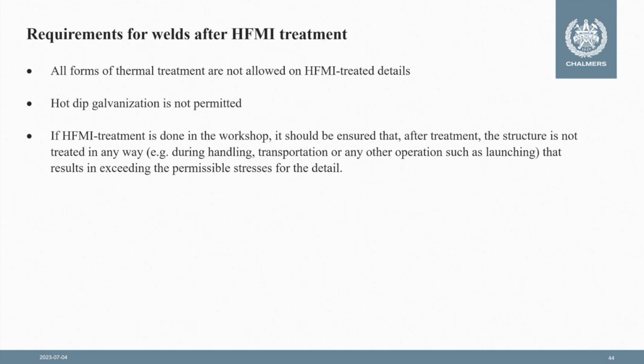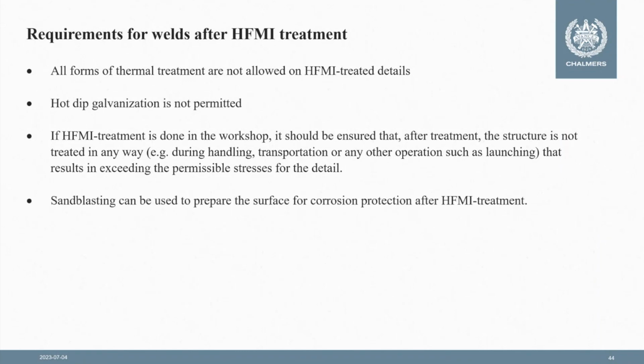If HFMI treatment is done in the workshop for new bridges, it should be ensured, of course, that no operation done results in a relaxation of residual stresses. For example, if the bridge is to be launched, there is a risk of very high localized stresses that would result in a relaxation of the residual stresses, or maybe during erection, operation, transportation, and so on. So that needs to be taken care of.